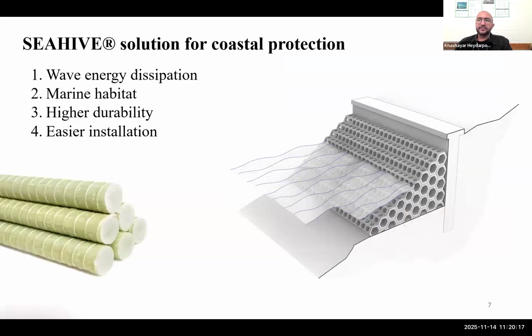As a result, SEAHIVE is introduced as a solution for coastal protection with these benefits. The first one is wave energy dissipation, and it happens when the water passes through the void units of the SEAHIVE, and it leads to more efficient wave energy dissipation. And the cavities in units are suitable for growing marine habitats. And they also have a higher durability due to the potential for using FRP reinforcement that are corrosion resistant. And they are also easier for installation, and the installation of the SEAHIVEs will also be explained almost at the end of the presentation.